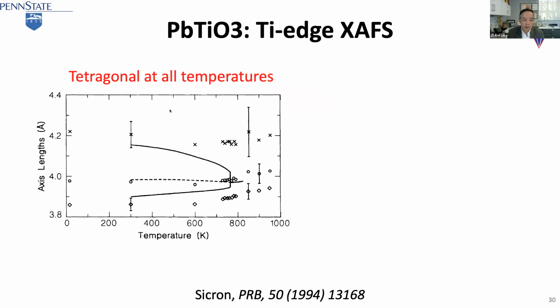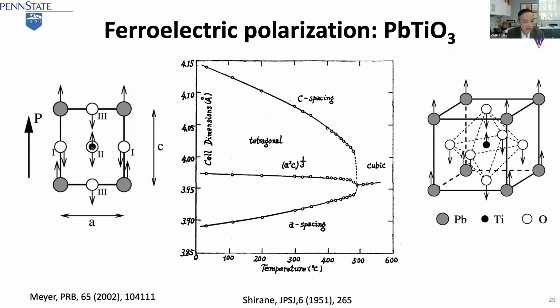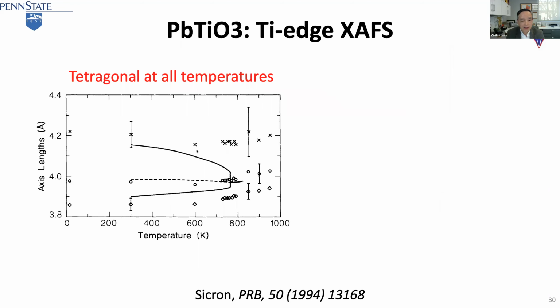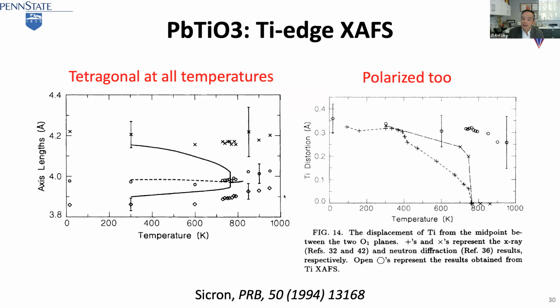And then we can do experiments too. People find that if you look at the titanium atom, which is in the center here, it is actually always displaced. You always see a ratio, even above the macroscopic cubic. You still have the titanium tetragonally displaced, c and a, even way above that temperature. And also polarization, as the atom is displaced, by these XAFS experiments. But by X-ray and neutron, it's cubic, no polarization.